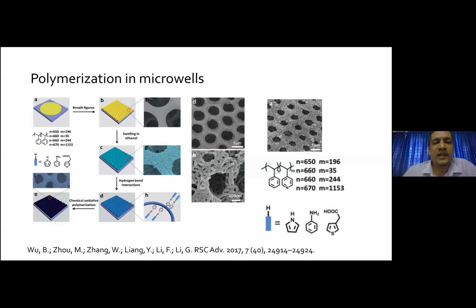So when you make this kind of block copolymer as a polymeric thin film, you align this vinyl pyridine in such a way that it is exposed close to the core of the microwells. Even if it is not aligned at the time of breath figure formation, you can always use ethyl alcohol vapors to pull these molecules closer to the interior of the microwells. Once you align the vinyl pyridine to a larger extent to the interior, you allow these molecules to be hydrogen bonded with small molecules such as pyrrole, aniline, thiophene, and thiophene carboxylic acid. So this forms the monomer.